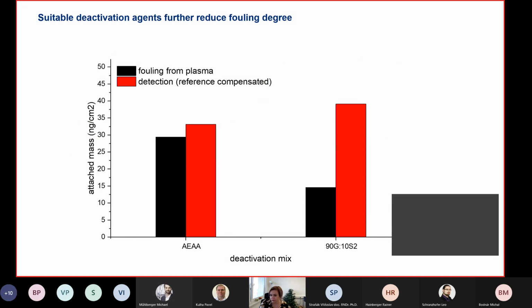Very important is also to understand the molecular mechanism of functionalization. So we developed, for instance, a strategy using certain deactivation agents, with which we can further improve the fouling resistance of the final coating after the attachment of biorecognition elements. Here's just a figure of our chemical apparatus, which we developed in our laboratory. It's quite unique because we can produce more than 100 substrates per day with different dimensions and different materials. Typically, the methods used for characterization of the developed coating are infrared spectroscopy, SPR, spectroscopic ellipsometry, and also QCM, the quartz crystal microbalance method.